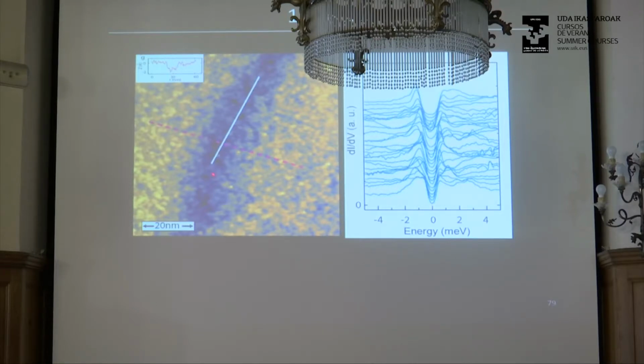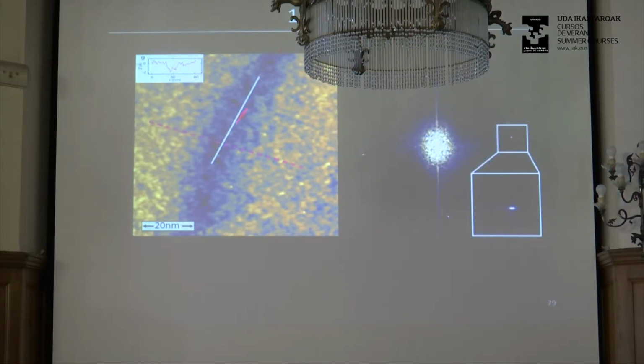However, if you take spectra along this line, you see nothing. You just see a superconducting gap. Now the question is, what do you expect to see? I'll tell you in a second. However, this is not the right kind of domain wall. The reason we know that is the kind of domain wall we're looking for should show a pi phase shift in the crystal structure from here to here. If you do a Fourier transform of this, these are the Fourier transform peaks. You can see it's a single dot, and anything with a pi phase shift should show split peaks. Okay?